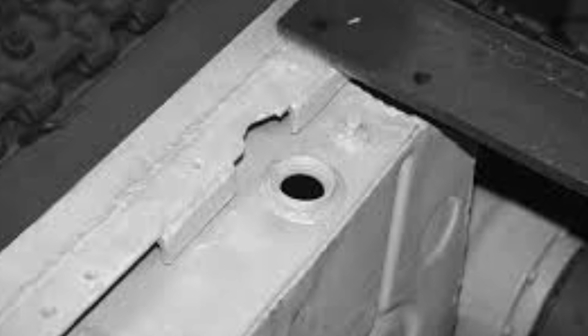The automatic weld passed all ballistic and metallurgical tests on the first try. A manual welder averaged a 30% first-time pass rate on that particular seam because of the awkward angle and the length of continuous welding required. But the most important result wasn't visible in the numbers. It was visible in Klavdia Kozireva's face when she watched the automatic head work. She had been welding that exact seam by hand for 8 months.